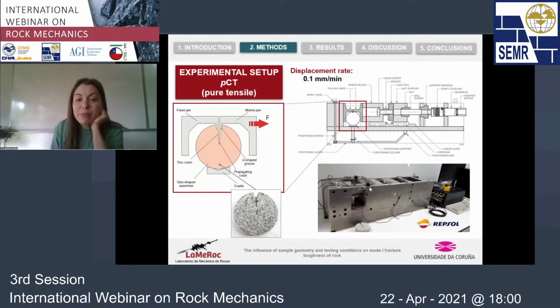And in the case of the displacement, we have two LVDTs placed here on the upper part of the device. So these LVDTs measure the displacement of the steel jaw, which is attached to this block here. So we have two LVDTs, but the measure is the same for both of them. And we have also a clip gauge here, which is attached between the steel jaws, and it gives us the same magnitude.